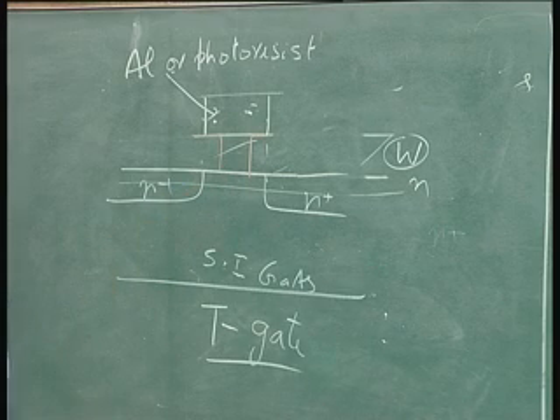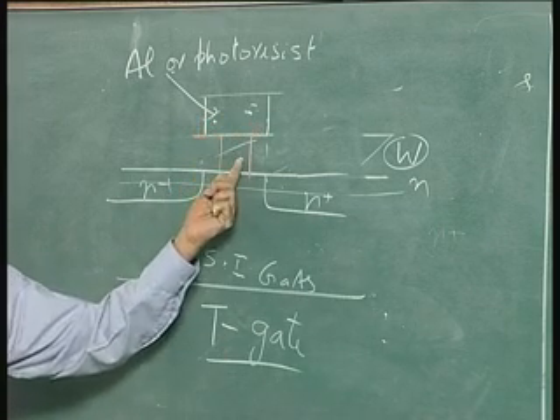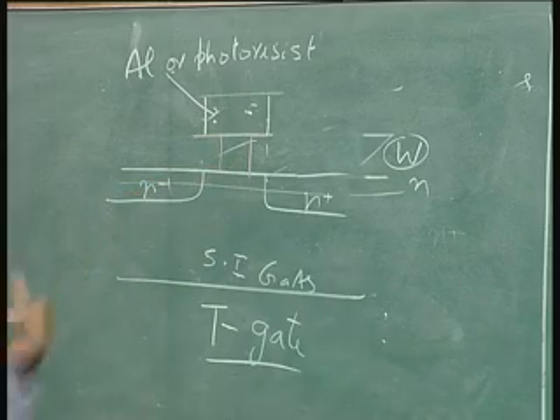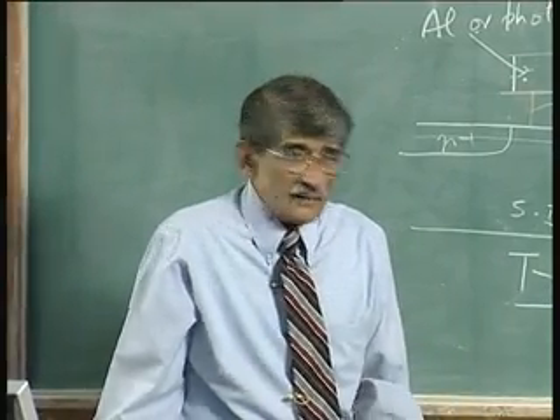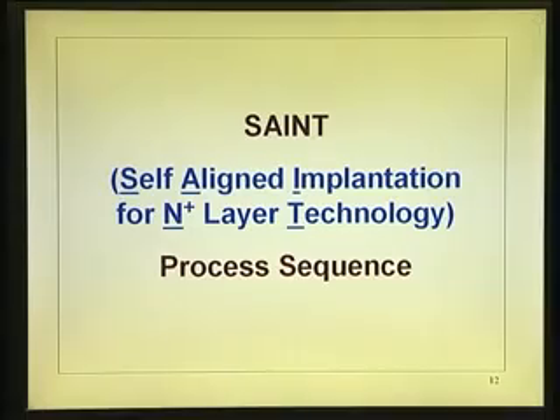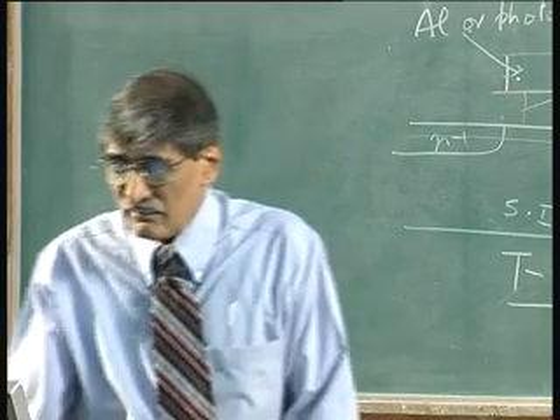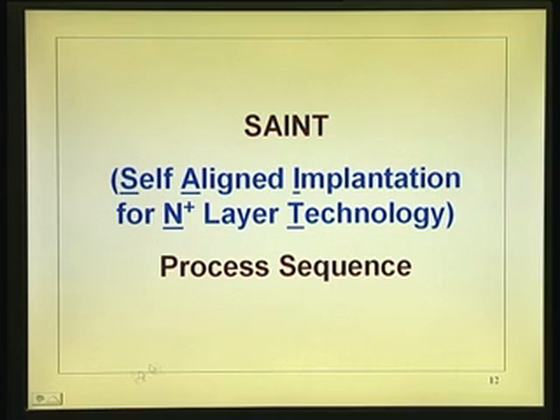The key thing here is to realize a structure like this, but without metal, and put the metal at the end, aligned with respect to that. That technology I will discuss right now, because the entire focus now is to obtain self-aligned structures. We have discussed two types. One of them has the problem of high series resistance, and both of them have the problem of using refractory metal. So, the method that has been quite popular, though a bit more complicated technology, is SAINT, self aligned implantation for N plus layer technology, SAINT.